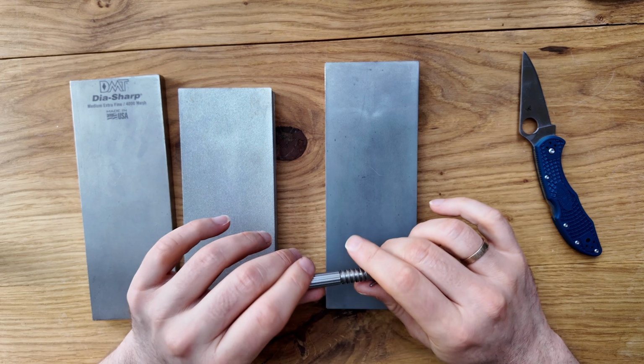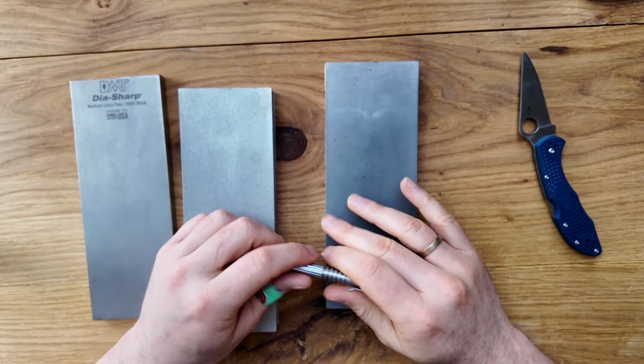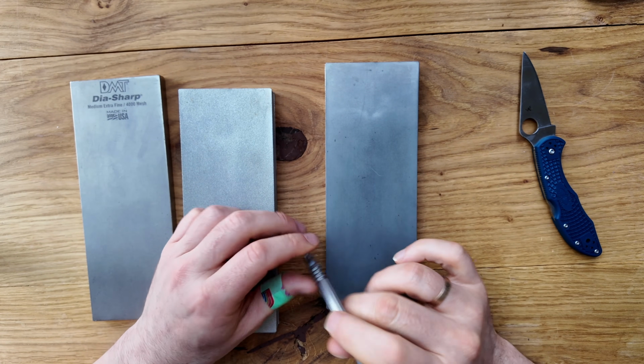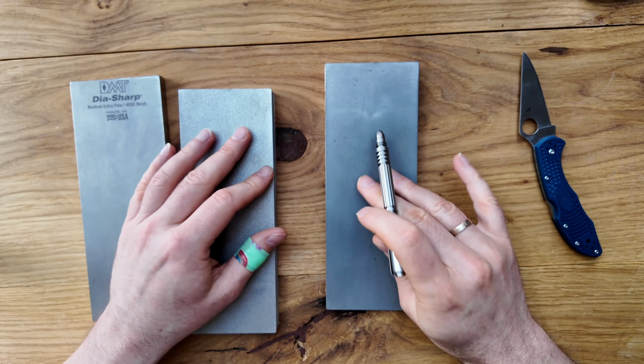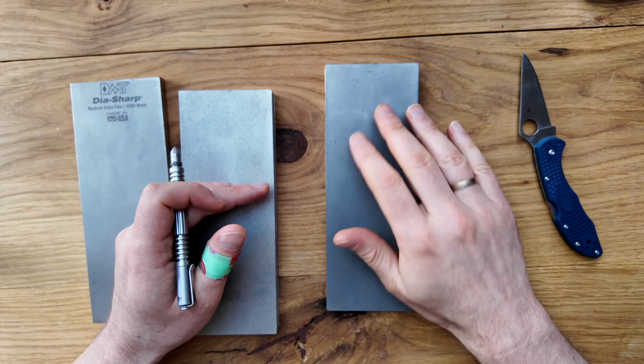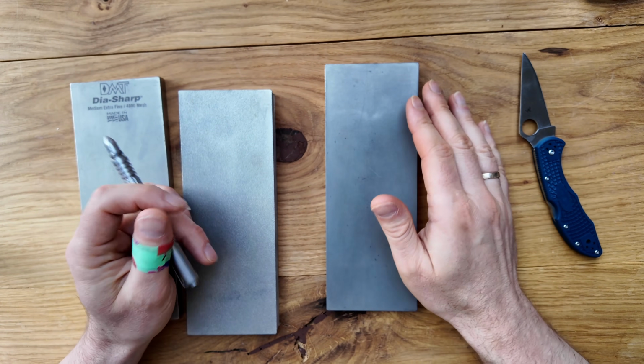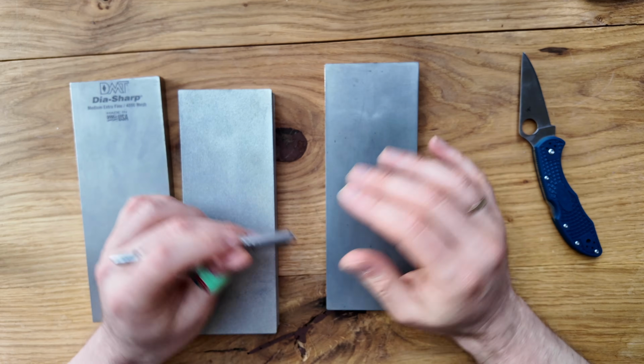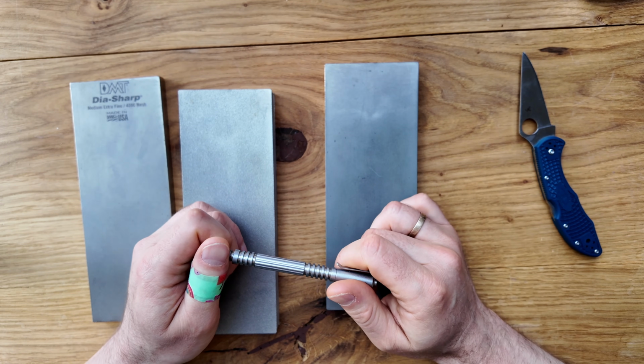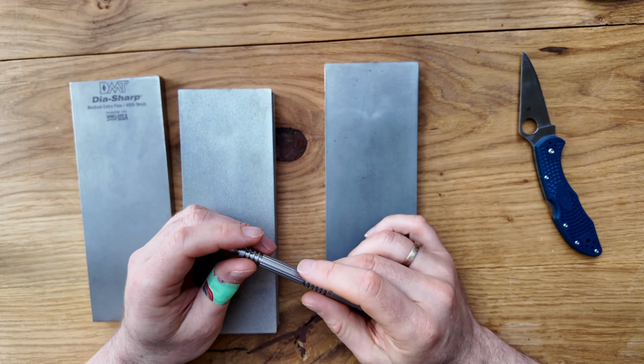So the 600 now. The normal grain size for the 600 grit is roughly 25 to 26 microns. The bulk of the measurements cluster between 20 and 30 microns. That is right where they should be for a 600 grit stone. So the distribution is nice and tight. There are no wild outliers, no dramatically oversized grains. This stone gets a solid pass. Then we move to the 1000 stone.